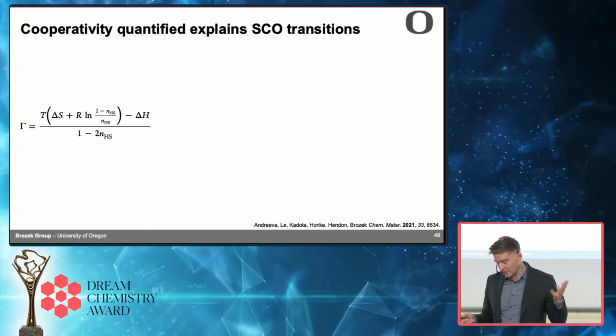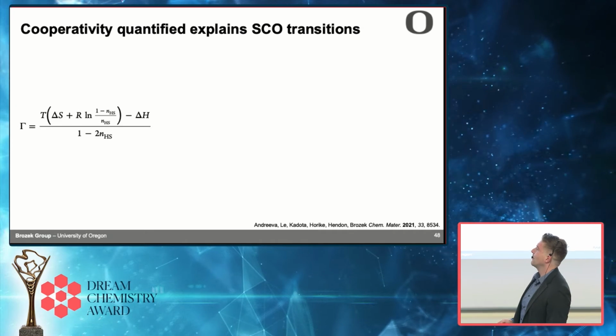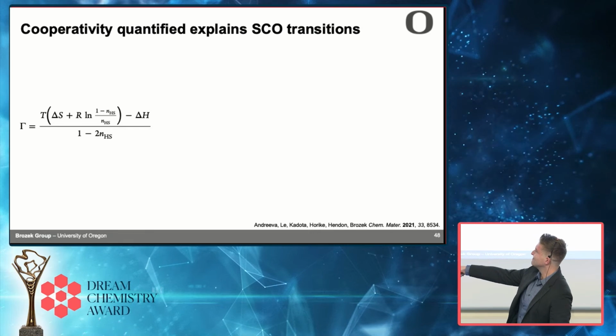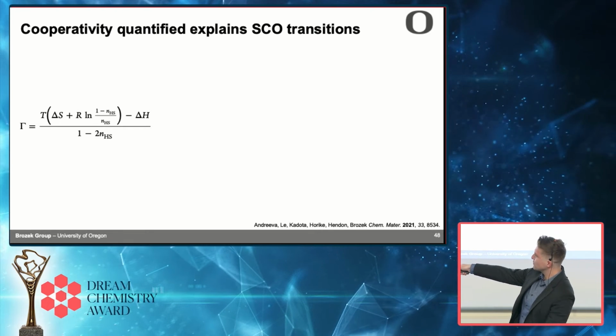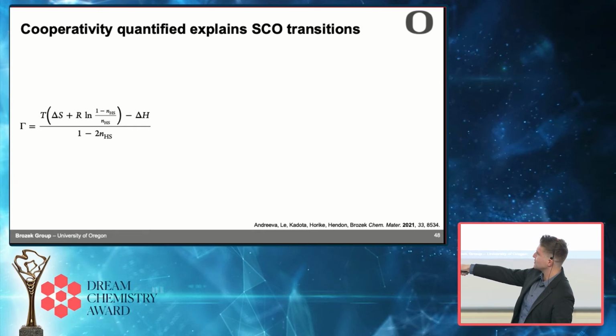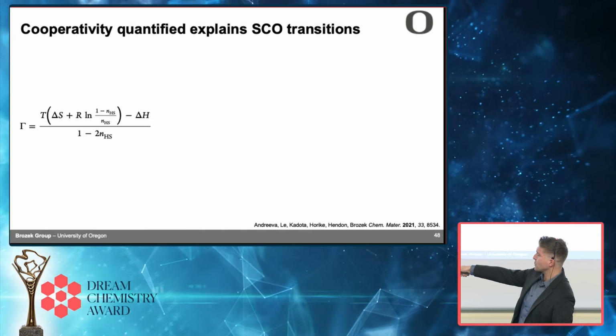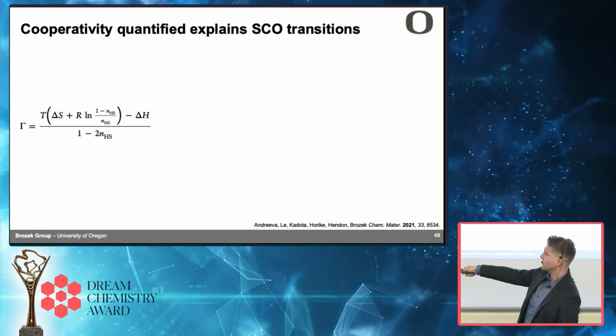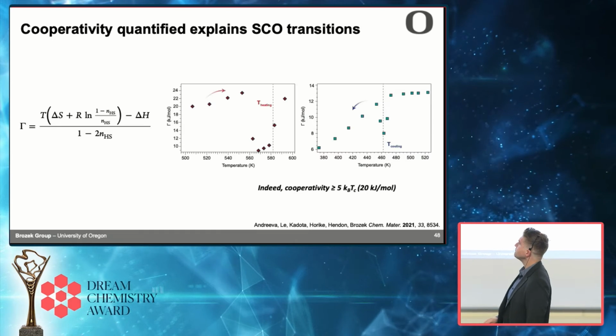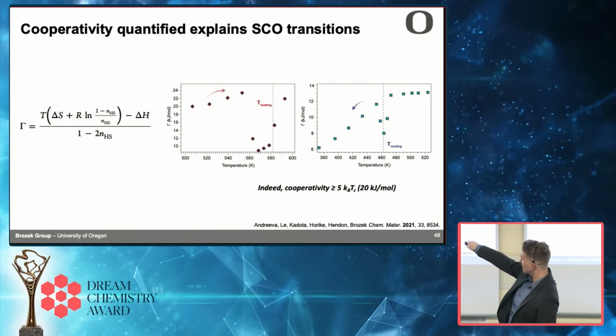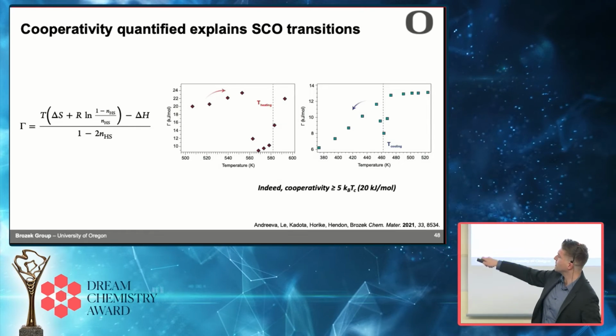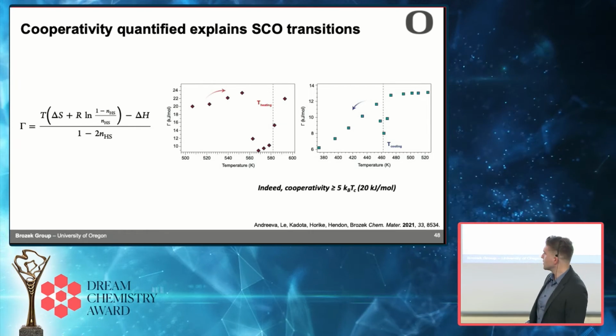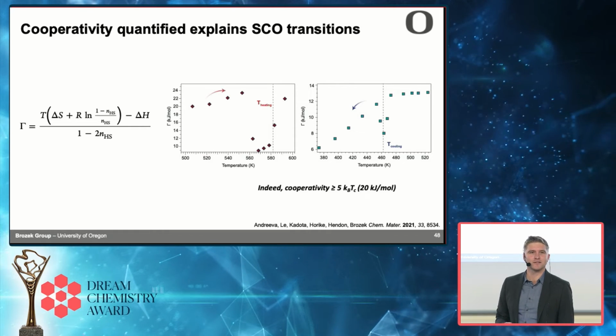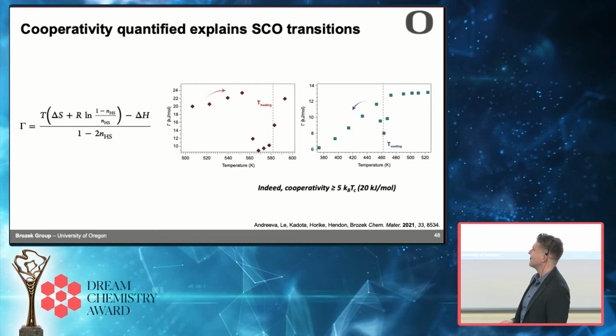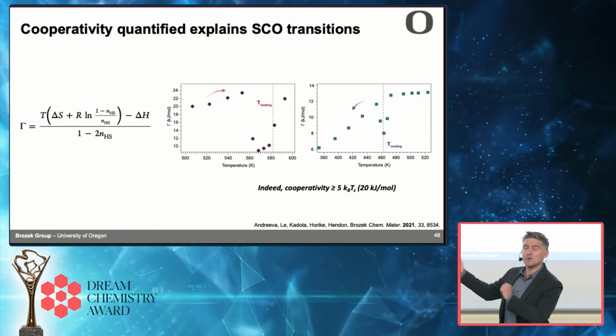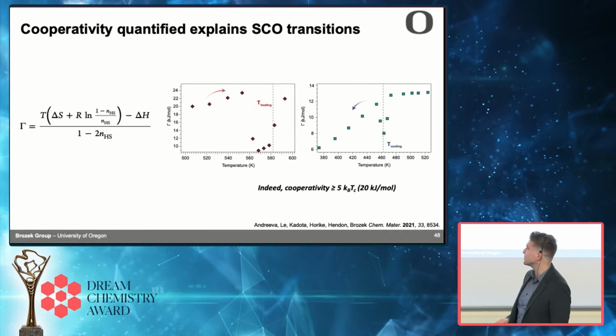Okay, so there's this idea of cooperativity. What the heck is this? So we're looking around more in the literature. People can measure it. They call it gamma. If you do the calorimetry experiment I showed you before, you can get delta H and delta S. And so at a given temperature, if you know how much of your metal sites are in the high spin state, that's this value here, you can figure out what cooperativity is. Okay. So we can do this, and as a function of temperature, we can back out what cooperativity is. And we get values of about 20 kilojoules per mole. It turns out that's exactly 5 times kT for this material. So exactly like people had predicted in the 70s. Cooperativity, whatever it is, I still hadn't figured out at this point what it means, but it's behaving the way that it's supposed to.